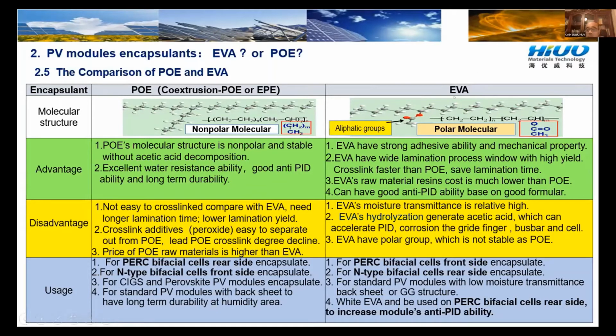Okay. Now let's move to EVA. EVA has strong adhesive ability with good mechanical properties. EVA also has a wide lamination process window with high yield, very easy to operate. The cross-linking is faster than POE, which can save a lot of lamination time. Generally, I think pure POE compared with EVA will have at least a 5 to 6 minute difference in lamination time. And EVA's raw material cost is much lower than POE and easy to buy, and it can have good anti-PID ability based on a good formula.